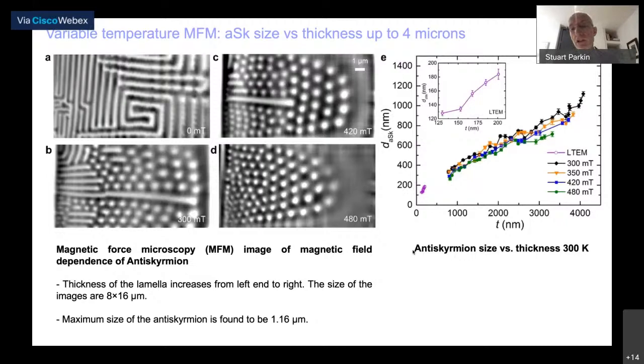And on the right-hand side, you can see a plot that the diameter of the antiskyrmion increases from 100 nanometers when it's thin to more than 1 micron when it's 4 microns thick. And the size of the antiskyrmion exactly matches the period of the helix because both are derived from the same physics, the ratio of the Dzyaloshinskii-Moriya exchange, related to this broken inversion symmetry of the tetragonal Heusler structure, to the Heisenberg exchange.